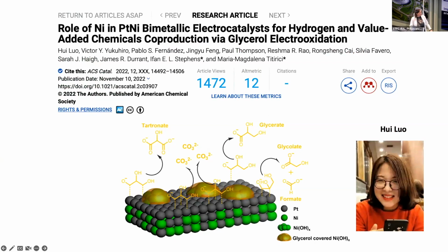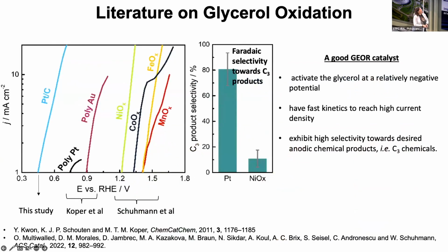So strongly recommend her. So now, if you look at glycerol oxidation and you take literature and compare it, this is our study on pure platinum. I mean, we didn't do pure platinum, but we also tested pure platinum. This is poly platinum, polycrystalline platinum, gold. And you see, as you go to more sustainable catalyst metal oxides, that your potential is increasing a lot, the potential at which you could actually activate this glycerol.